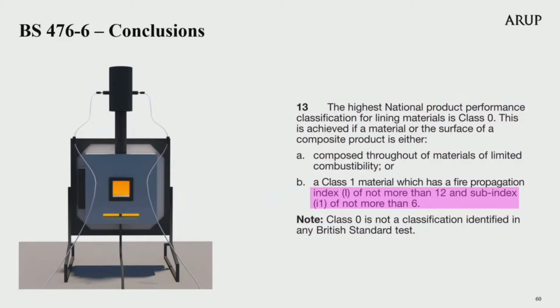To sum up, the Part 6 test is the fire propagation index test and is based on the temperatures measured in the chimney. The product tested is then assigned little s1, little s2 and a little s3 sub-index. These are averaged across 3 tests to obtain the sub-indices little i1, 2 and 3. The sub-index little i1 is therefore an average of measurements taken during the first few minutes of the test only, when the heating dose is relatively low.